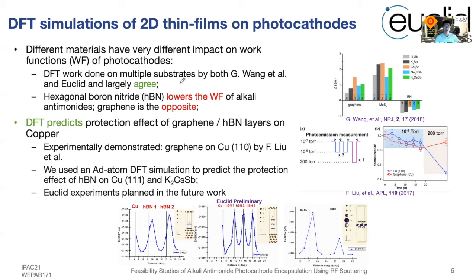You can find a lot of detailed work in this paper, but mainly the results show that 2D thin films, especially hexagonal boron nitride, can preserve the work function of alkali antimonides. Specifically, HBN can even lower the work function of alkali antimonides. Graphene is the opposite, but still the additional work function added from a monolayer of graphene is very small.